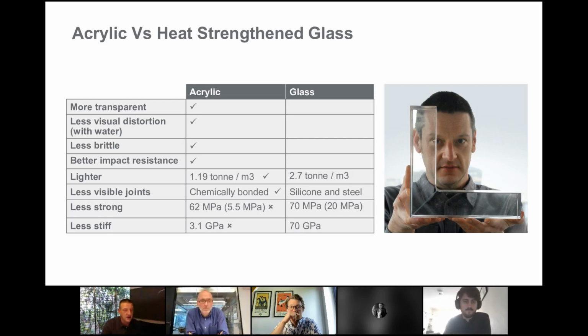However, on the negative side, it's much less strong. It has a working strength of about 1/4 of a glass structure, and it's also much less stiff by a factor of over 20, which means that for a given size of acrylic beam, if you put the same load on a glass beam and an acrylic beam, the acrylic beam will move 20 times more. It will deflect 20 times more. So that's a very significant